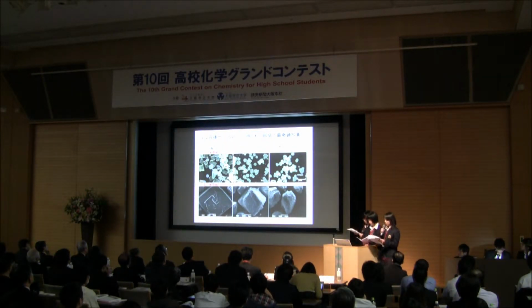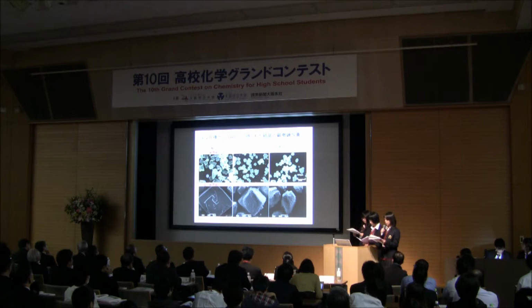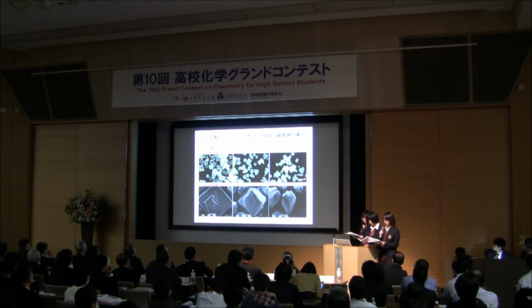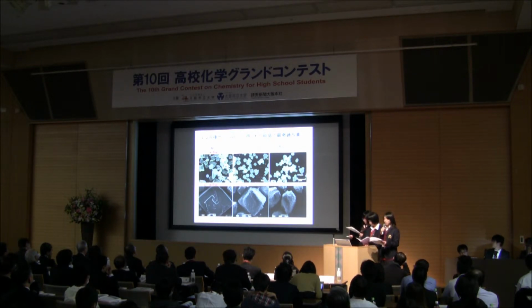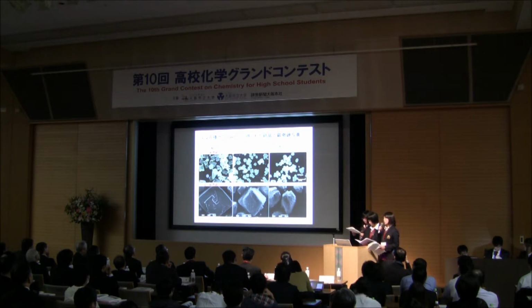As you can see, silica is the best to form crystals. We also found that different shapes of crystals were found in different gels. For us, this is a very interesting discovery. In silica, beautiful square-shaped crystals and sphere solids appeared. In gelatin, crystals were not so beautiful. They had a less square-shaped and rough surface. In agar, crystals like oval balls appeared.